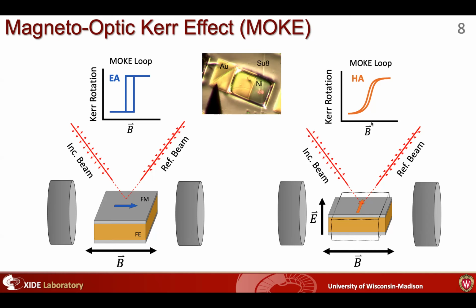And then we hoped to show by applying an electric field along the thickness of the PMN-PT and sweeping a magnetic field, if it rotates 90 degrees, then we can see a hard axis closed loop instead. So rather than rotating the sample to measure different in-plane directions, we want to kind of use voltage to see if we can observe an evolution between these two states.